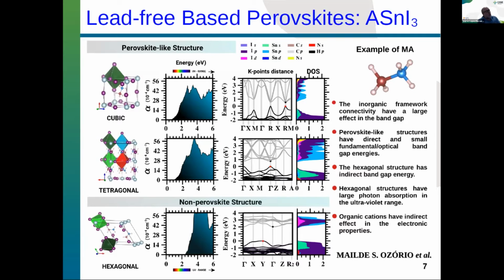If you take this cation out of the structure, keep the structure frozen, because if you don't keep it frozen, it can collapse. To take the monovalent cation out of the system, pop it out. If you calculate the absorption coefficient, it is nearly the same. This means that what drives the absorption are the octahedrons of the system.